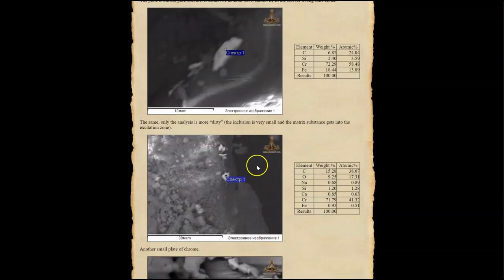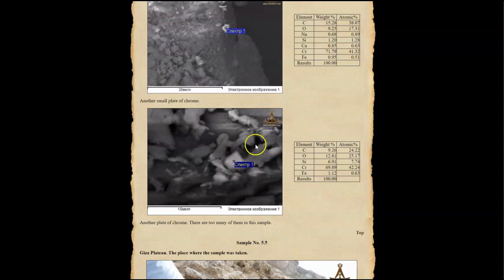Here is another small flake of chromium, 71% chromium. And yet another one, this one at 69% chromium. So in this sample, there are tons of microscopic chromium flakes. Where did these chromium flakes come from? That is still to be determined.